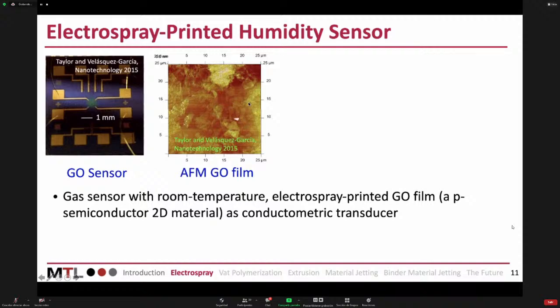You see, it's made of flakes of graphene oxide, which is a 2D material that is a semiconductor. What is important to understand is that typically semiconductors have conductometric behavior. So they get some stimulus and they change resistance. Then you can measure that change, and based on that, you can infer the quantity of the chemical stimulus that they received. With that, we have been able to create sensors as thin as 20 nanometers. These imprints are made of graphene oxide flakes, and the pile of flakes is thinner than 20 nanometers.